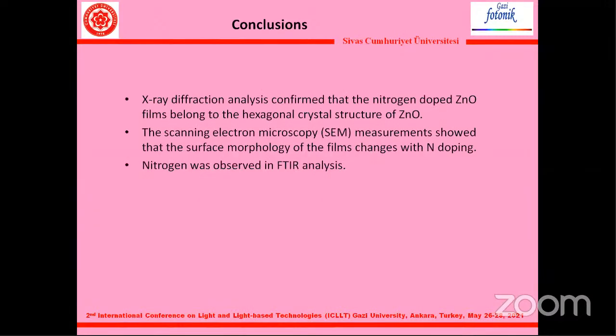Conclusions. Finally, X-ray diffraction analysis confirmed that the nitrogen-doped zinc oxide films belong to the hexagonal crystal structure of zinc oxide. The scanning electron microscopy measurements showed that the surface morphology of the films changes with nitrogen doping, and nitrogen was observed in FTIR analysis.